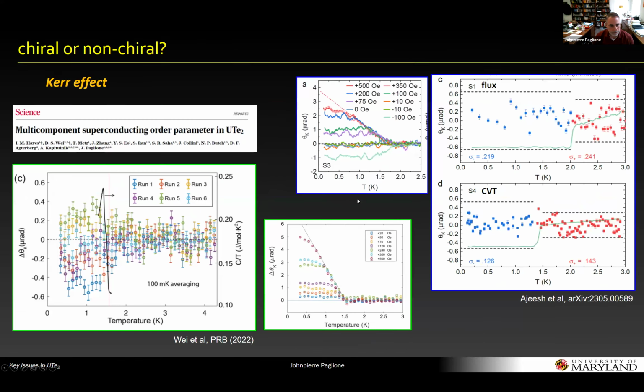Okay. Now, Kerr effect. The moment you've all been waiting for. I think this has been talked about in many papers now. The original work in our paper, collaborating with Aaron Kapitolnik's group, showed a spontaneous Kerr effect measured in these samples. And together with the observation of a double TC in the heat capacity, we claimed that this was evidence for multi-component ordering.